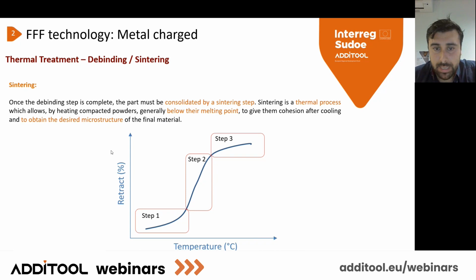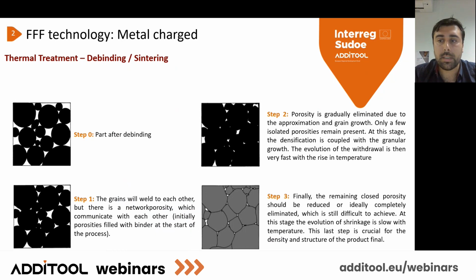Important thing is, when we raise the temperature for the sintering, all the polymer will dilate and cause a lot of retraction of the part. So the part will be reduced after the sintering. We have to master exactly the proportionality between the programming, the manufacturing, and the final geometry we will have after the sintering. It's around 19 to 20, 25% of retraction, and it's different between the X, the Y, and the Z. That's why I explained a little bit before.